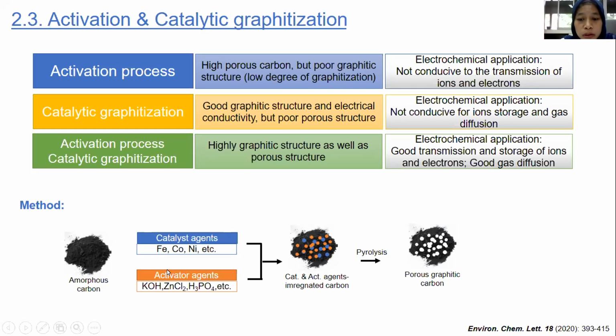This is the method. The activator agent, like potassium hydroxide and etc., is used to stimulate and develop the porous structure, and the catalyst agent like iron, cobalt, and nickel is used to catalyze the formation of the graphitic structure. This combination method could produce carbon material that has good porous structure and high graphitic structure as well.